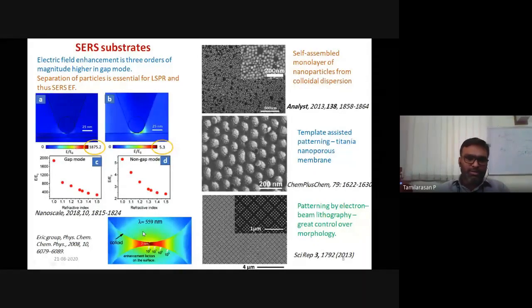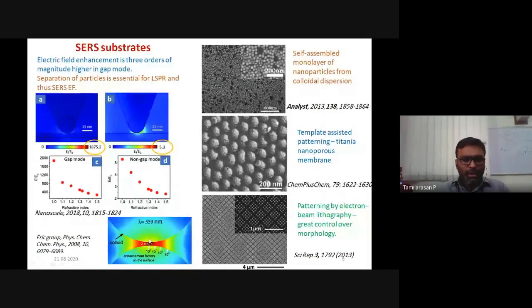Why? Because let's see the hotspot produced between two particles. If you see this region, this is the lowest distance between the two particles, where you have the highest enhancement factor, because already we have seen the interparticle separation will exponentially drop the enhancement factor. So at the lowest distance, it has very high field, like 10 power 8. When it is going radially out from this point, then you are losing the enhancement factor quite rapidly. As I already said, it drops as an exponentially decaying function. So even if you have a well-defined system, if you put a molecule here, that will produce a stronger signal than putting a molecule here.